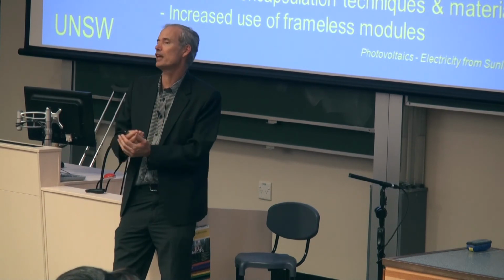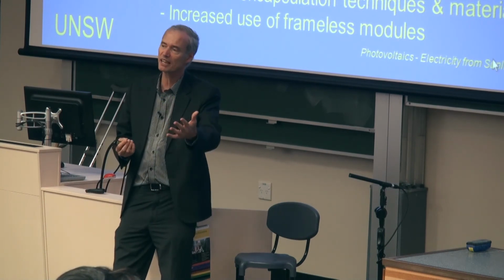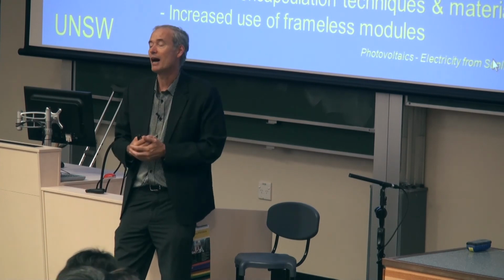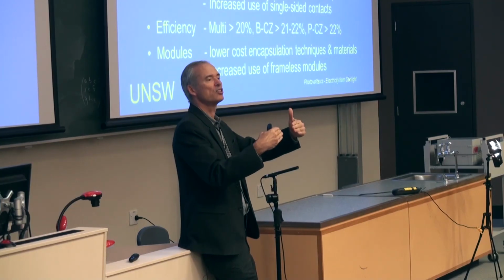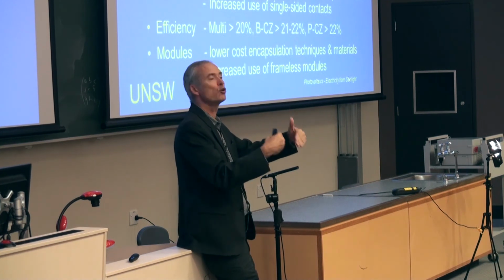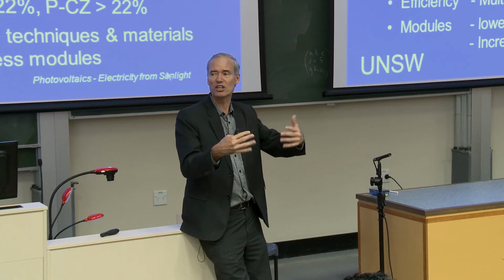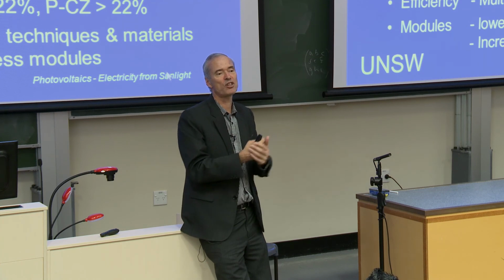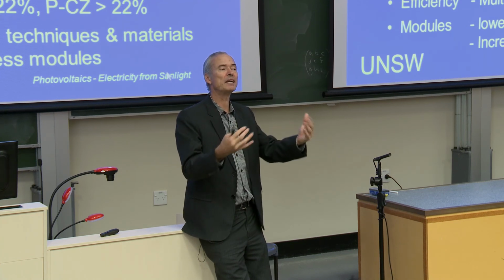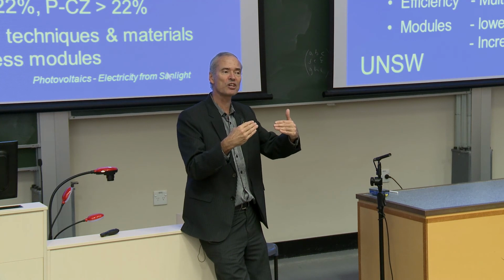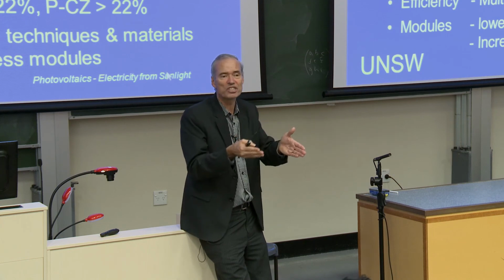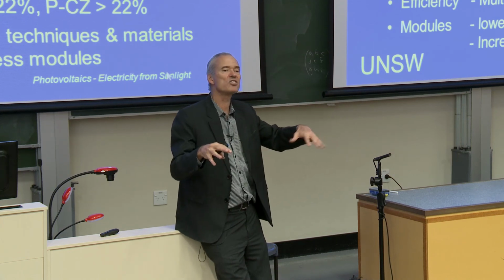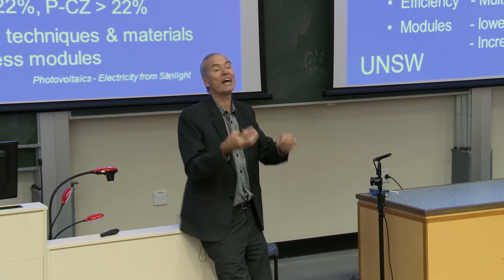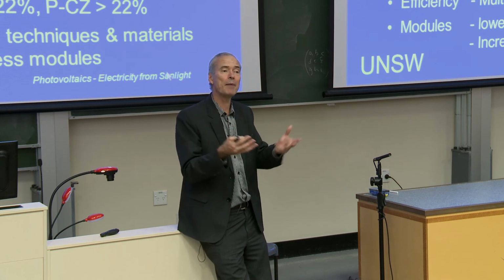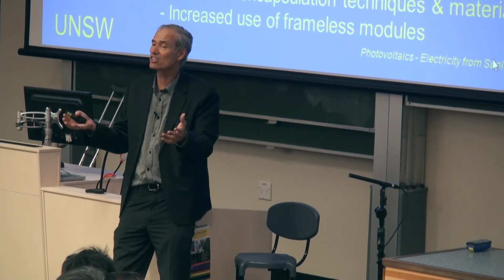There's been a lot of good developments in recent years that I've talked about in previous lectures of this nature each year to do with the front surface. DuPont deserves a lot of credit. They've done a great job improving the metal paste, improving the techniques for applying the metal contacts to the front surface. It's enabled a big improvement in the emitter design at the top surface of the solar cell, the contacting mechanisms, the contact resistance achievable, reduced shading losses, more lightly doped emitters that allow you to get better blue response and higher voltages. All of that has been happening in recent years, very much thanks to DuPont.